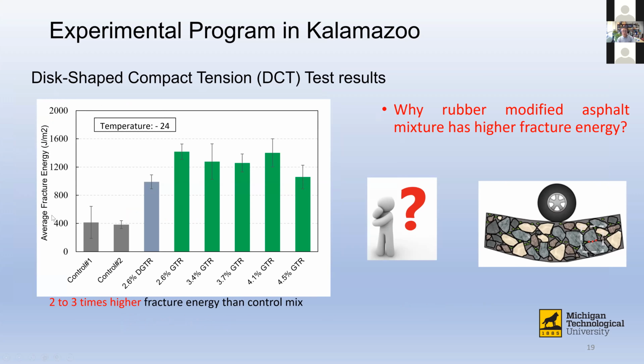You can see here a piece of results I have is average fracture energy, versus some other samples you can see here. Control 1 and control 2 are basically the normal asphalt we use on the roads, like say US 41. Here it is basically those kind of dense graded asphalt materials. You can see their fracture energy is about 400 joules per square meter. And the rest of those bars are with a certain amount of rubber inside. Of course, sometimes more rubber, less rubber. Let's ignore those things. You can see roughly the results are about 1200 joules per square meter.